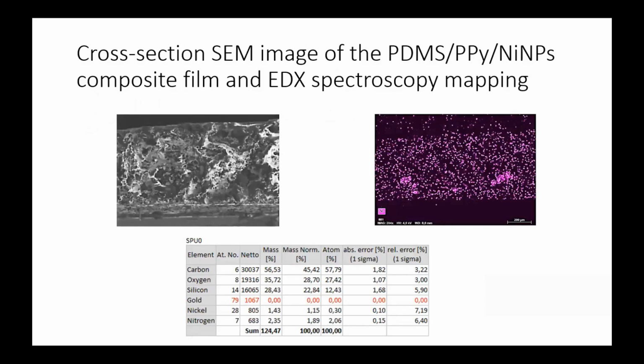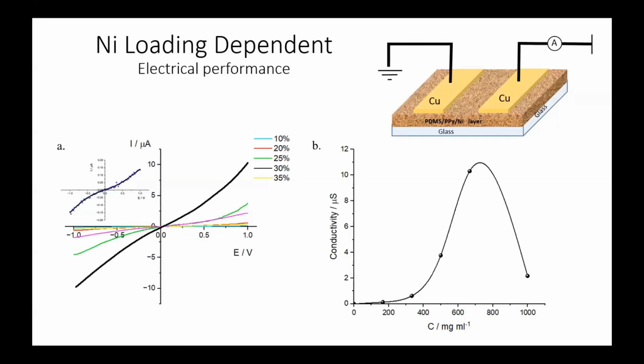When we check in SEM, the cross-section SEM imaging with EDX, we can see that the nickel nanoparticles are very, very homogeneous around the latex. Another phenomenon is that the loading of nickel particles on the film gives us the electrical performance. Here we have the percentage by weight of the nickel in the latex.